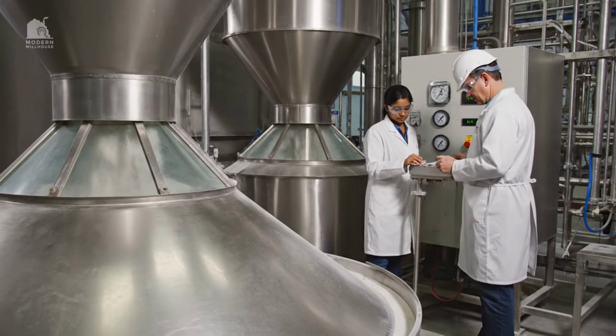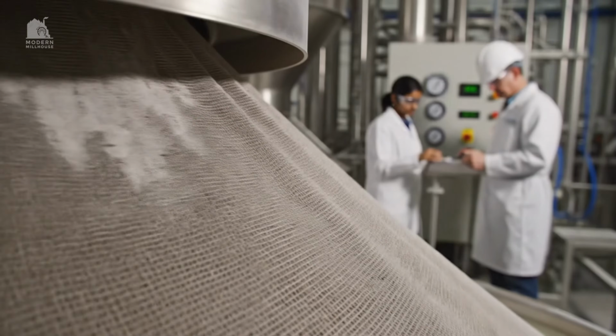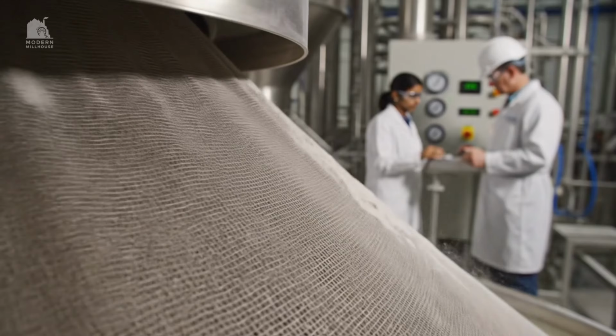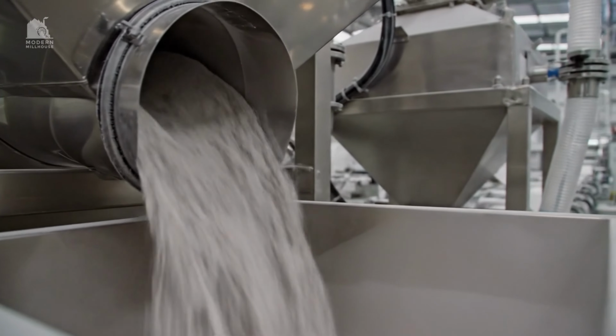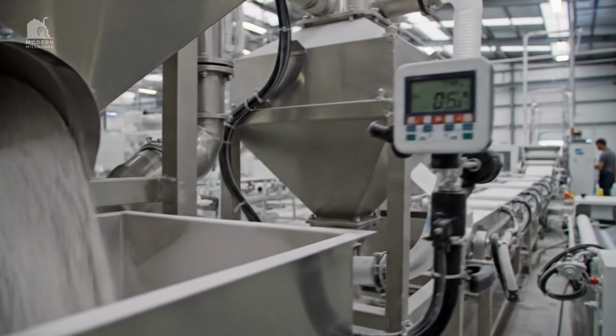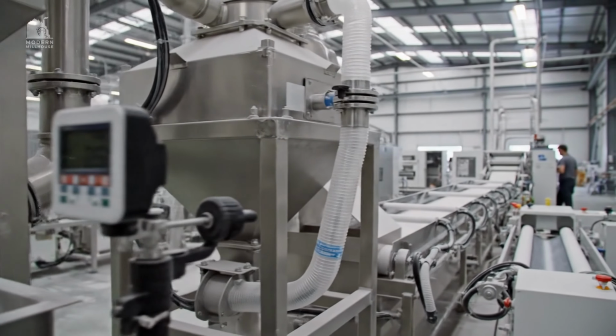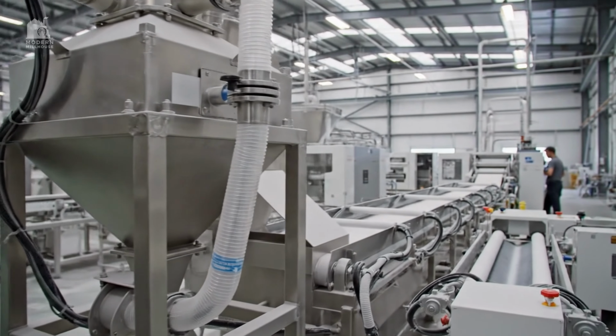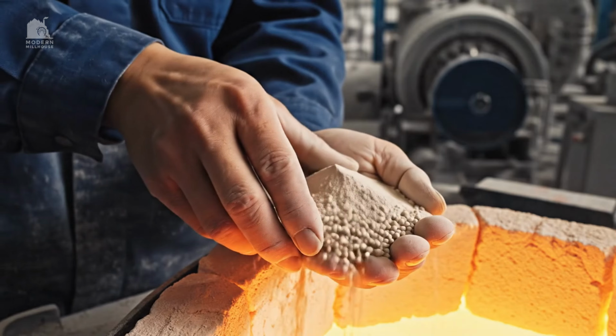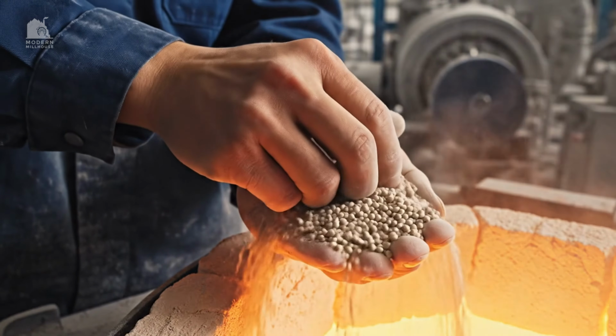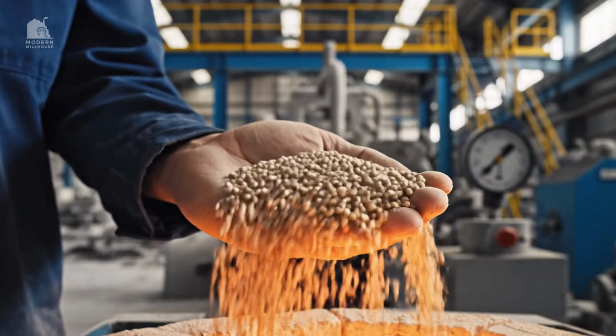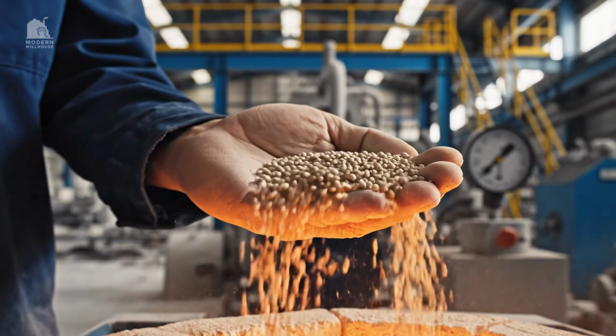Operators watch cyclone collectors and filters that capture fine powder from exhaust air. Recovered fines may be blended back carefully. Too many fines can change flow and pressing behavior. They also watch the temperature of exiting powder. If it is too hot, granules can clump in silos. If too cool, moisture may be too high for stable pressing.